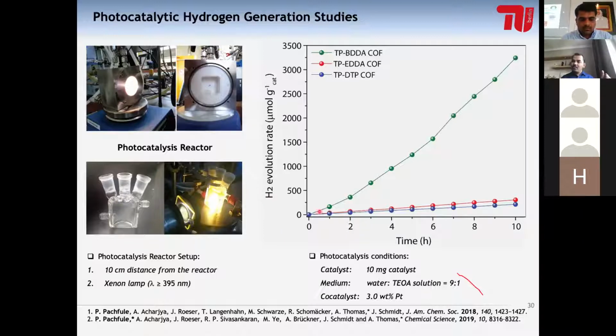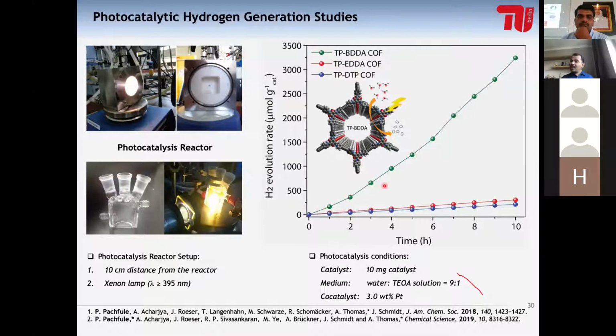And then we mixed everything together, evacuated this particular gas chamber with argon multiple times, removed oxygen from it, and started the reaction shining with this xenon lamp. And what we observed, most interestingly, here we can see the hydrogen evolution rate on the y-axis, and the x-axis shows the time. And now you see that TP-BDDA COF having the diacetylene moieties shows the highest hydrogen uptake as compared to other 2 counterparts. And mainly the reason could be these COFs have diacetylene moieties in their backbone, they have lowest band gap, and it absorbs in the visible region.